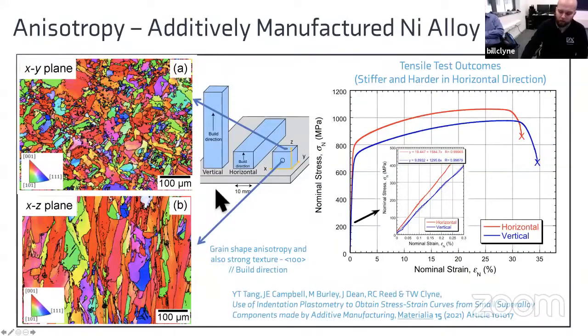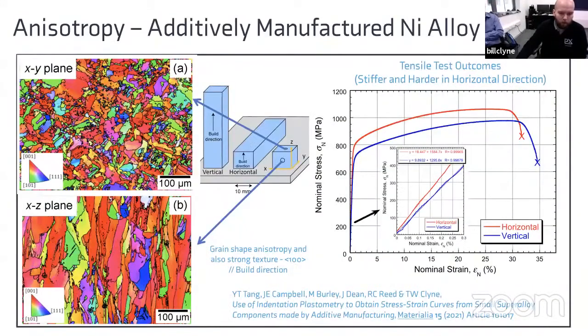So, if we look at anisotropy first, one area where we might see significant plastic anisotropy is in additively manufactured metals. This example here is of a nickel-based superalloy, and we can see on the left-hand side EBSD scans from two different orientations. This one in the XY plane shows a relatively equiaxed grain structure, and this one in the XZ plane shows that there's clearly been directional growth along the build direction. So it's clear in this case that we've got a strong 100 texture parallel to the build direction, which is what you would expect in a nickel-based superalloy.